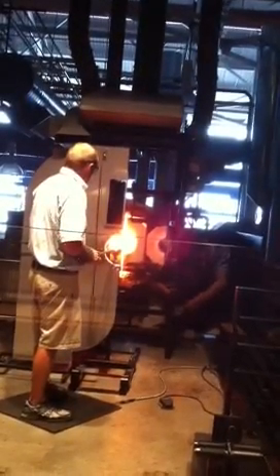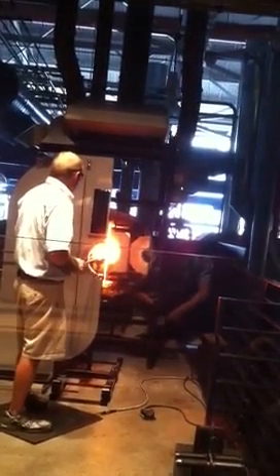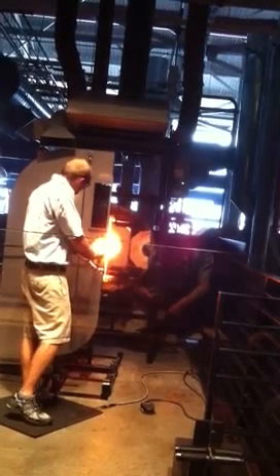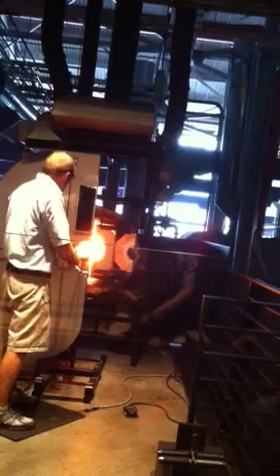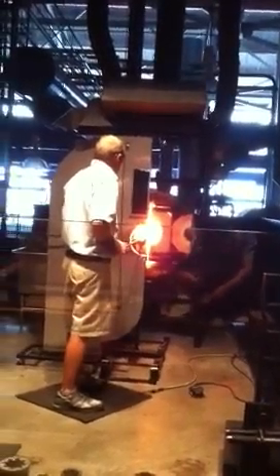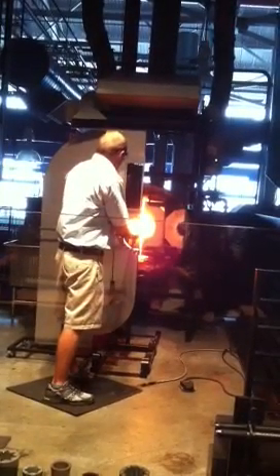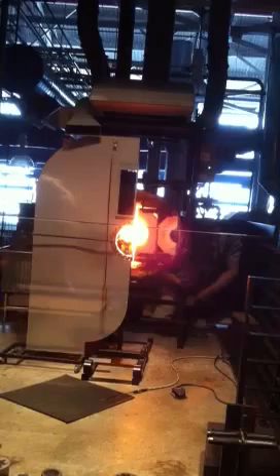She is just localizing the heat on the top of the glass. It's very important that she doesn't let this glass get too cold. If the glass starts to cool too quickly, this will create tension on the outside surface and it's going to crack. As the glass cools, it shrinks — the outside surface cools faster than the core, which causes the glass to crack.